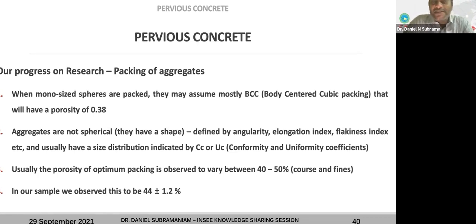So what we did is we did some analysis of putting all the aggregates into a mold without cement or water. We found that the porosity is about 44%, whereas if you take body centered, you would assume a porosity of 38%. But here we found actually 44%, which is almost like a simple cubic structure, right? But that is due to the shape and other characteristics of the aggregate. So we are not going to get in there and discuss that.